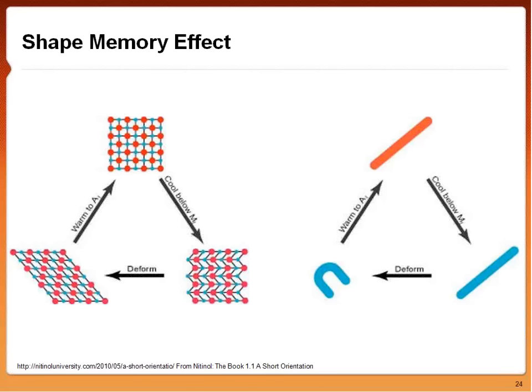So when we look at a piece of nitinol material that exhibits the shape memory effect, we start with a nitinol material in the austenite phase, the high temperature phase. We cool it. Cooling creates the twin martensite. We apply stress to it. The martensite accommodates that stress by forming detwinned martensite. And then finally, when we apply heat to it, we form it back into the ordered austenite crystal structure.